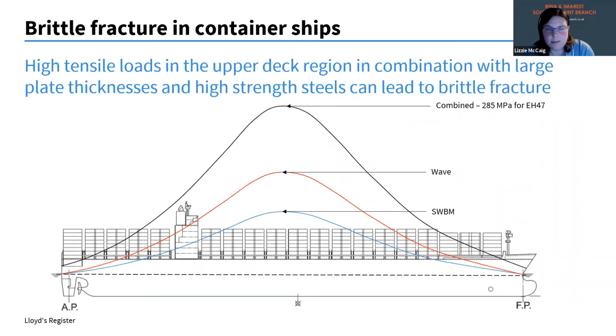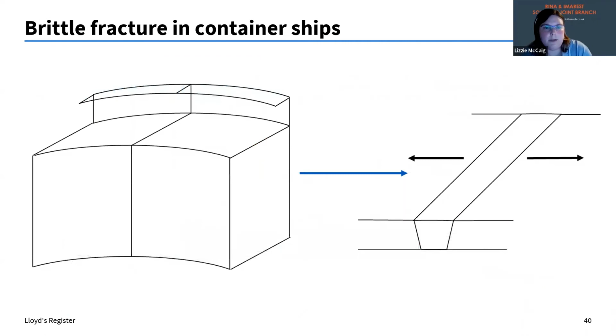The problem, though, is that these container ships also have very high tensile loads in the upper deck region. So you're combining very, very high loads with very high strength steels, and as a result, this can lead to brittle fracture. This is because container ships are normally hogging. That means that the weld seams of the upper hull girder are normally being pulled apart rather than being compressed. For those of you who are familiar with fracture mechanics, when you compress a crack, you do slow the rate of growth, whereas if you start pulling it apart, then you increase the rate of growth. So this is another reason why this is a particular problem for container ships.